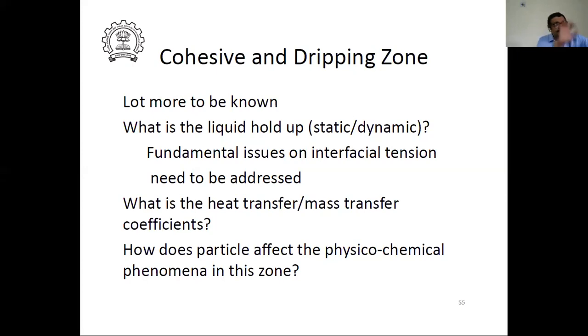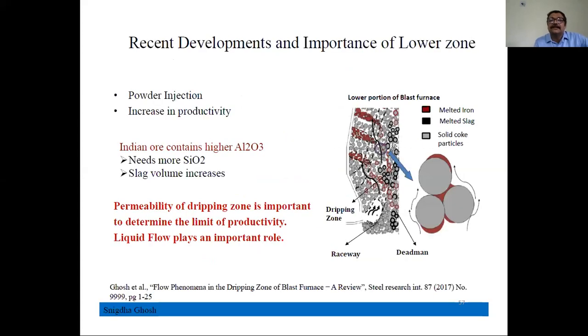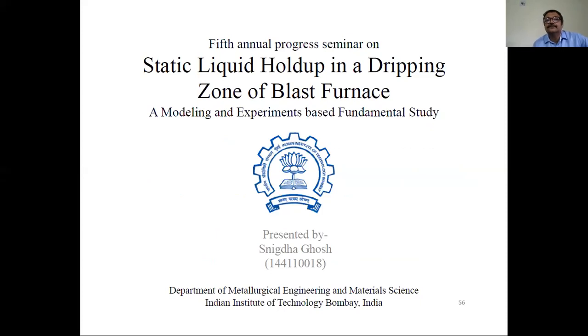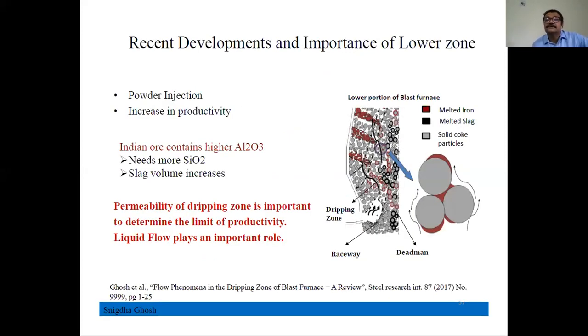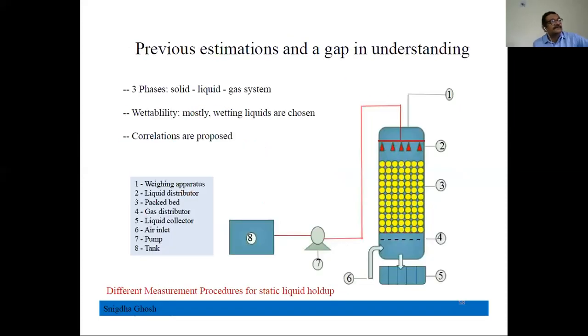This is done by my student Snigdha Ghosh, who will soon be faculty in one of the IITs. These are very nice experiments which were done by chemical engineers a long time back. You take a bed of particles, pass the gas from the bottom, and spray liquid from the top, uniformly. As you keep increasing the gas flow, the liquid is also trying to come down. At one point the liquid cannot fall down, and it will flood the area. This is called flooding. It is very simple, and can be done even in the laboratory with water and pebbles, just allowing the gas to go up.